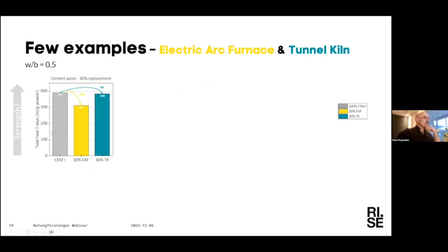Still at the cement paste level with 30% replacement, and to follow this, the heat that is released by isothermal calorimetry. And so the results are put here and presented with a 100% cement paste. So I mentioned earlier that this kind of value can be directly linked to the strength. But in this case, we have to be careful, because if we have, for example, free lime, this kind of material, when mixed with water, will give a really high exothermic reaction. So that will impact a lot of the total heat that you measured at 7 days.